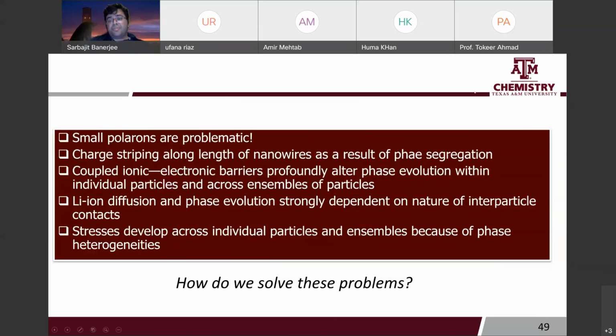Okay, and these coupled ionic electronic barriers profoundly alter phase evolution within individual particles as well as across ensembles of particles, and stresses develop across individual particles and ensembles of particles because of phase heterogeneities, right? So again, the lesson here about the importance of interdisciplinary research is relating things like crystal field splitting and the formation of a small polaron, all the way into the mechanical properties and the capacity loss that we see in real batteries, in something like a functional cell phone battery that you might be using, right?